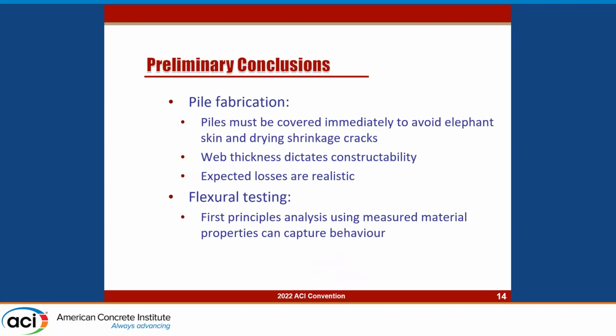We also found that our expected losses are really realistic compared to what we saw in the field. And then on the flexural testing side of things, we saw that if we use first principles analysis using the properties that we measure in the field, we can pretty accurately predict how these flexural tests are going to go.